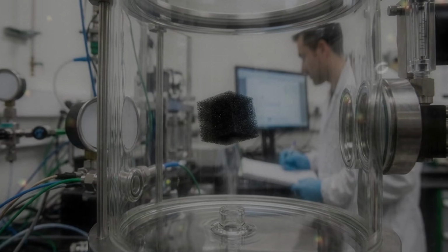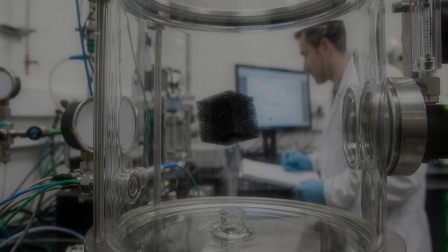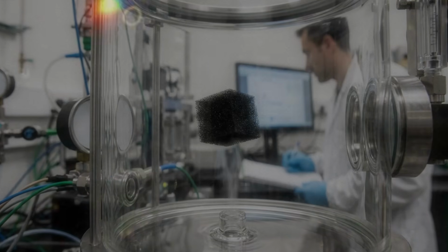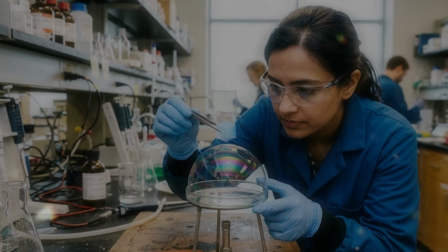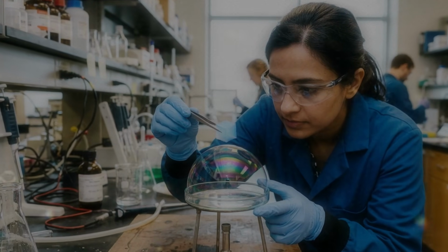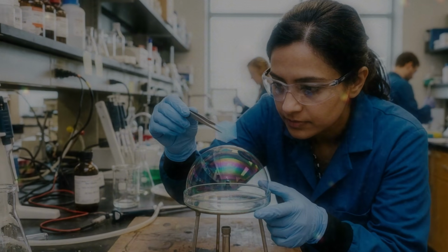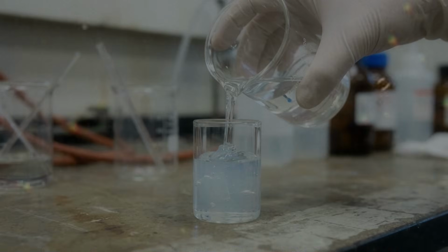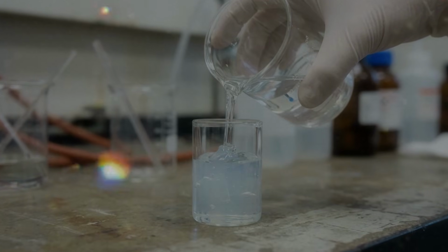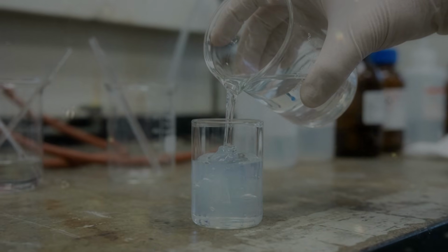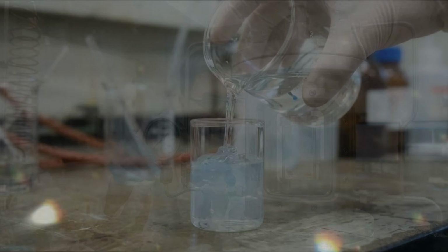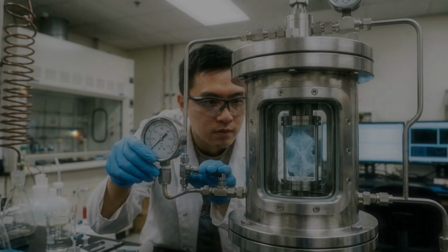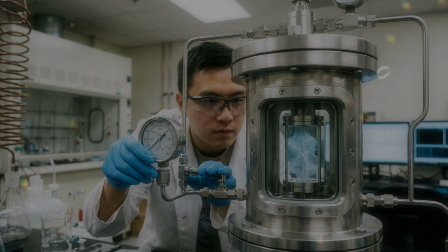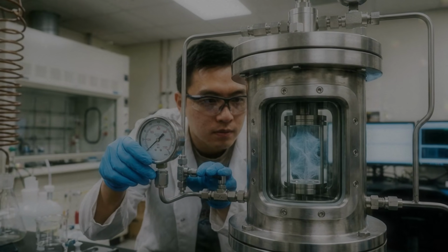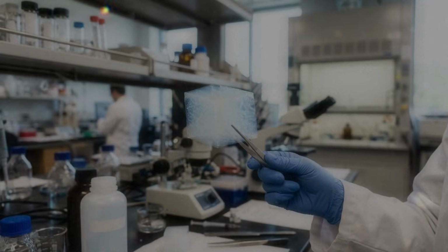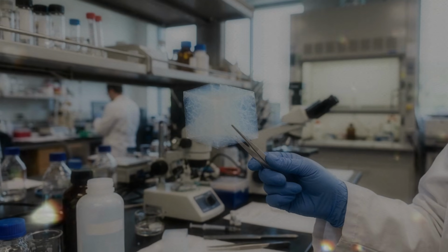Researchers can also build the structure around a temporary template. A polymer foam, metal network, salt crystal, or other scaffold provides a shape. Graphene-based material coats the template, and the template is later removed. What remains is a hollow network that copies the original architecture. Templates offer control over pore size and connectivity. A random gel may contain a wide range of openings, while a prepared scaffold can produce a more regular pattern.